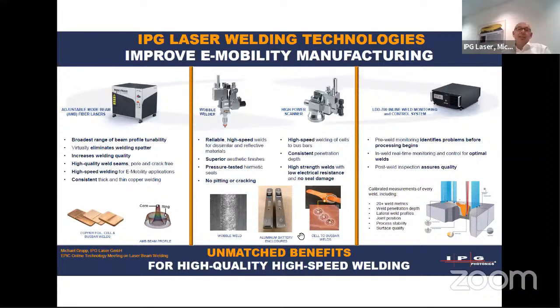Another option to optimize this weld quality, which is always the main key in copper welding, is to apply dynamic beam shaping. Dynamic beam shaping means that we apply scanning heads or wobble heads to move the beam very fast. It is known that a fast movement of the laser beam stabilizes processes in copper welding. And this is what we can do in a very limited space, for example, in a small circle or small lines, to get really reliable high-speed welds on these highly reflective materials or dissimilar materials. So we get very aesthetic finishes of the welds, for example, for sealing of battery cases, for connecting battery tabs to the battery cell, and stuff like that. So this is really consistent, very stable processes at very high speed by means of the scanner. So we can produce, for example, several tens of welds within 1 second on a cylindrical battery cell.